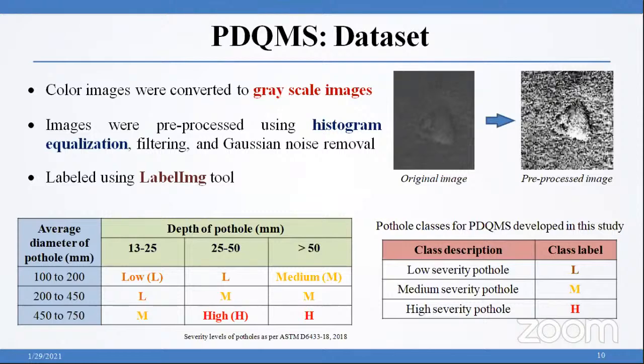So the data set had 41 images of road sections in the Andhra Pradesh state, and the image resolution of each image is 1280 pixels by 960 pixels. And as you can see, this is a snippet of an original pavement image. The quality of data usually plays a vital role in the efficiency of the detection rate of the algorithms. So images were pre-processed using image processing techniques like histogram equalization, Gaussian filtering, and Gaussian noise removal techniques.